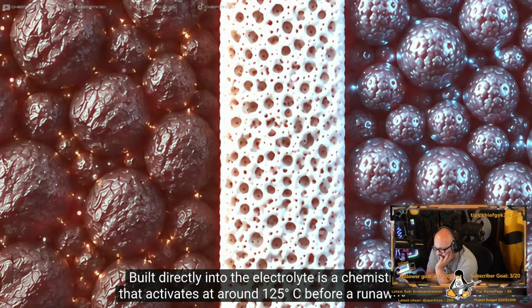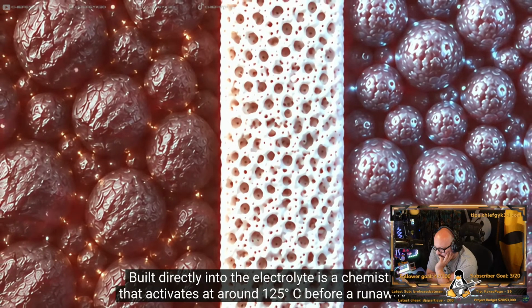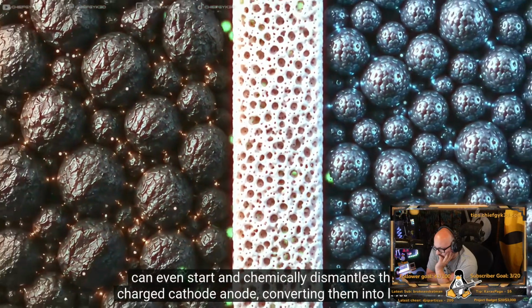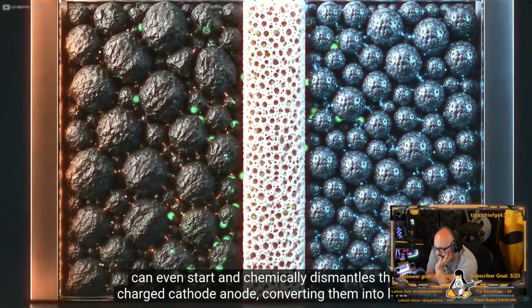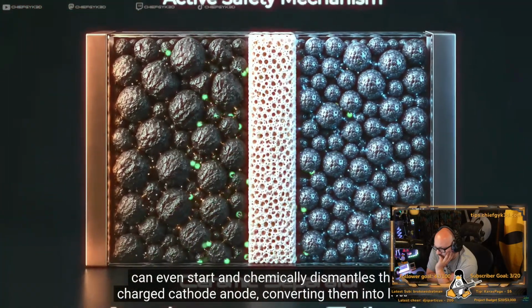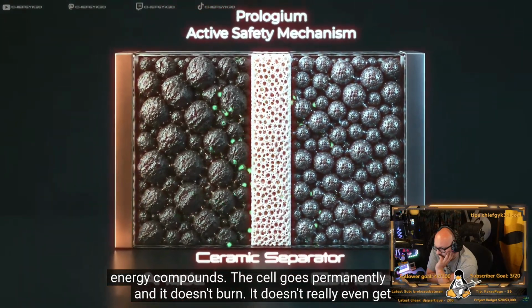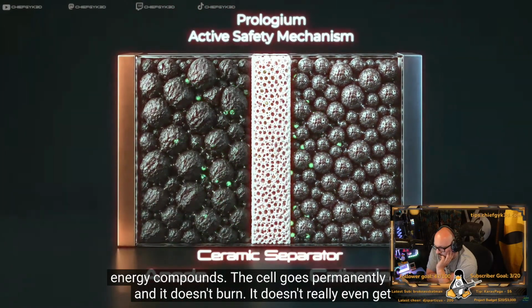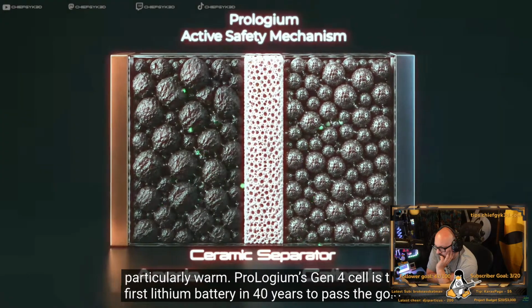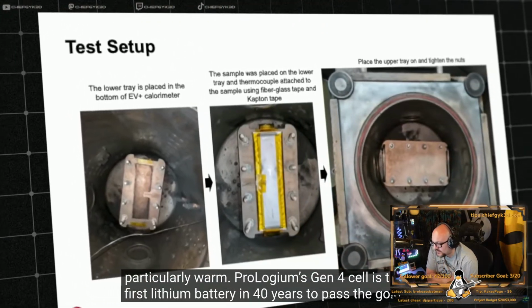Built directly into the electrolyte is a chemistry that activates at around 125 degrees Celsius before a runaway can even start, and chemically dismantles the charged cathode and anode, converting them into low energy compounds. The cell goes permanently dead, and it doesn't burn. It doesn't really even get particularly warm. Prologium's Gen 4 cell is the first lithium battery